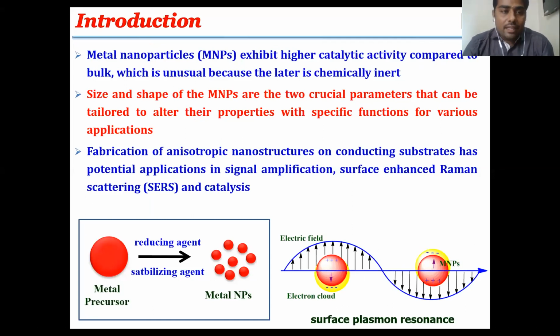Before moving on to the topic, a brief introduction about metal nanoparticles and metal nanostructures. Metal nanoparticles exhibit higher catalytic activity compared to bulk, which is unusual because the bulk material is chemically inert. Generally, metal nanoparticles are synthesized from a metal precursor with the help of a reducing agent and a stabilizing agent. As the size and the shape of the metal nanoparticles change, the color also changes. This is due to the collective oscillation of electrons in the conduction band, known as surface plasmon oscillation.